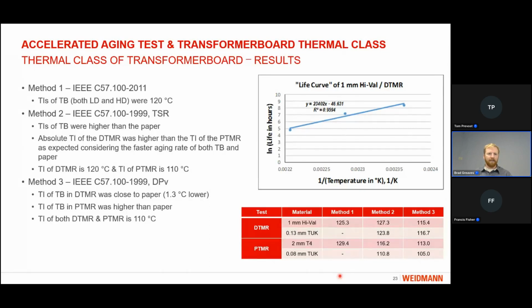However, as Tom described, this is then rounded down to the nearest 10 degrees based on the table that he showed. So defining the thermal index of both of these materials at 120 degrees C. Using method 2, where we looked at each material independent of one another, we're comparing the thermal index of the transformer board to the paper. And in both cases, distribution and power, we observed that the thermal index of the transformer board is slightly higher than the thermal index of the paper.